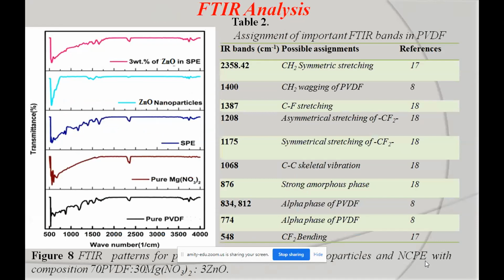Now, structural FTIR analysis. From FTIR analysis, this also confirms formation of the complex, and this is the FTIR pattern of pure PVDF, pure magnesium nitrate, solid polymer electrolyte, ZnO nanoparticles, and our optimum system, that is 3% of ZnO nanoparticles in the solid polymer electrolyte. And this table gives information about the peaks obtained in our pure PVDF.